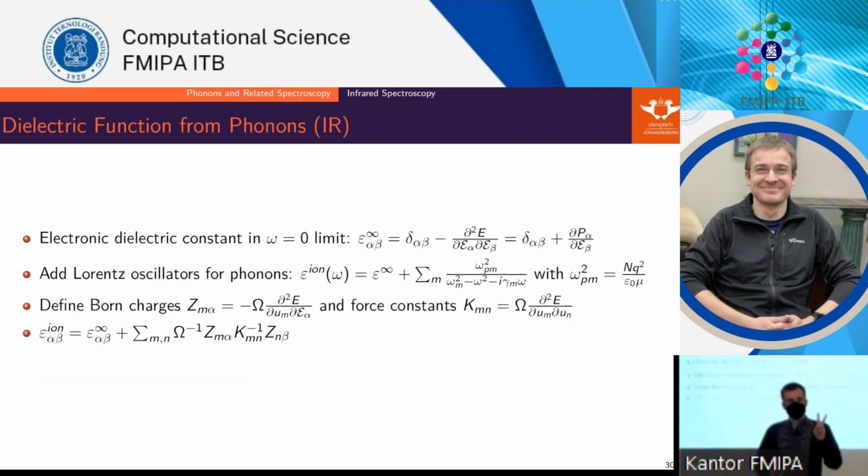So in the infrared region, there are two types of measuring the spectrum, aka the vibrational modes: Fourier transform infrared spectroscopy, and Raman. The first one is actually very easy. It doesn't require any additional software or anything. We just assume we have a Lorentz oscillator. Lorentz oscillator has a plasma frequency. That plasma frequency scales with the charge. And what is the charge in this case? Well, it's a dipole moment. When we have something vibrating, we create transient dipole moments, and these are basically proportional to how easy this mode is excited with light, for example.